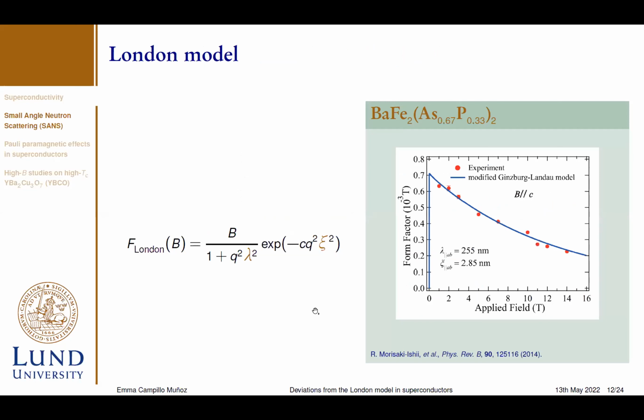The usual expression used to reflect the dependence of the form factor when we apply different magnetic fields to our material is the London model expression. The London model expression is just this first term in the equation, but since superconductors have a finite size of the cores of the flux lines that pass through the material, we have to include a Gaussian cutoff to account for this finite core size.